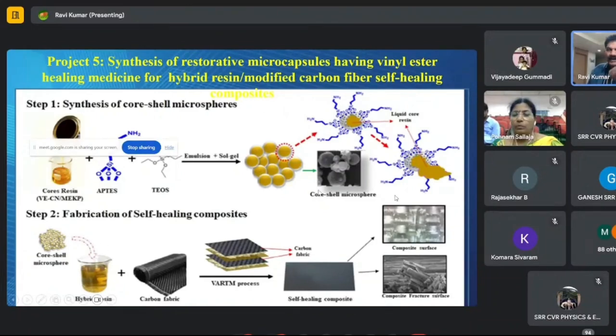Even if there is an accident on the surface, it can be cured by our material. It will be released immediately like an egg and yolk. The yolk will come out from the eggshell, and it will release, and the damage will be completely cured by these nano capsules. These capsules release the curing material that will be deposited on the surface, and you can see the depositions and you observe the composite fractures.